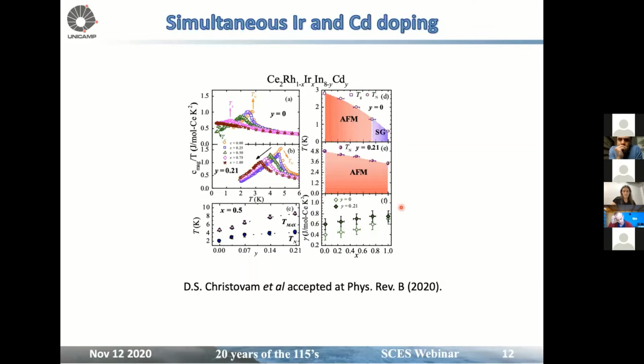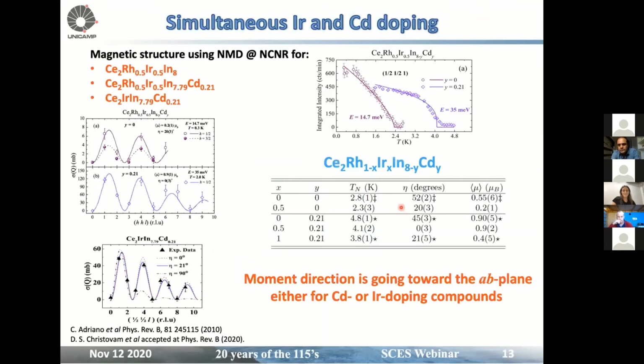We did magnetic structure experiments. We determined the magnetic structure for all of those 3 compounds, and those are simulations using experimental data, to give us the moment direction and everything else. So, that table summarizes our results so far. And what we could see is that basically both cadmium and iridium doping are making the moment direction go toward the AB plane. So that's a nice result.